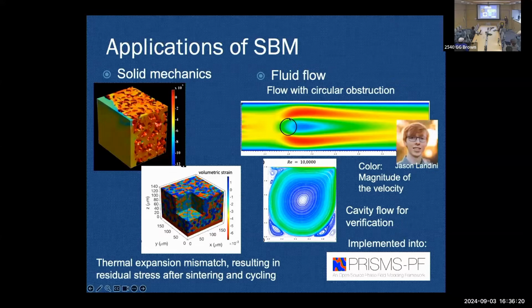You can also solve free flow. So there's a smooth boundary here, and this flow line is plotting the magnitude of velocity, and this thing is blocking. There's no solid boundary condition outside here, so you see blue, the magnitude of velocity is small. The flow goes up in the plateau here, but then it encounters this circle which is blocking, so it has to get around it. So there's a higher velocity on the side of it. It's been verified using cavity flow and things like that. And then it's implemented into Prisms-PF.